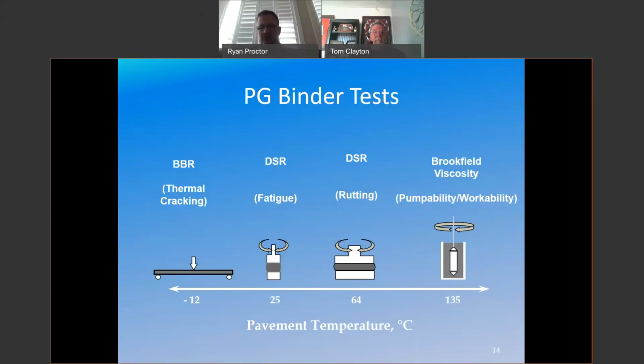So at the colder tests, we're looking at cracking. And I'll talk about this later, but that beam, we're trying to get to crack in the lab. The two middle tests are a DSR, dynamic shear rheometer. And in that test, and I'll focus on this later, you're looking at the performance maybe under road operating conditions with fatigue of the road over time and with rutting potential. And then as these new tests and new criteria were put in place, people were having issues making binders that had so much polymer in them that they couldn't pump them. So that last test on the right is really just to make sure that a hot mix plant can pump the material as they use it.